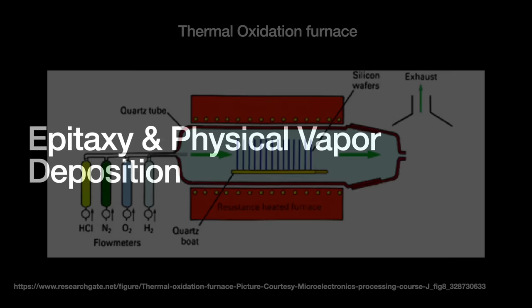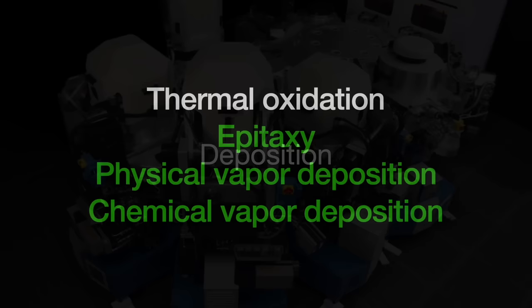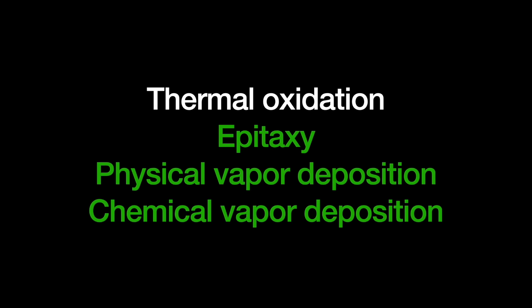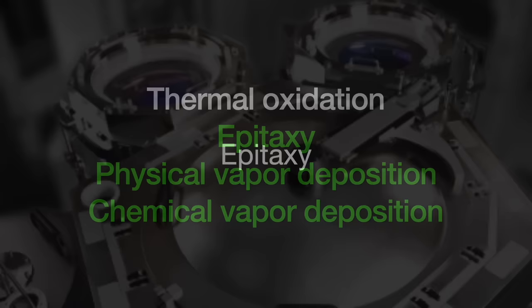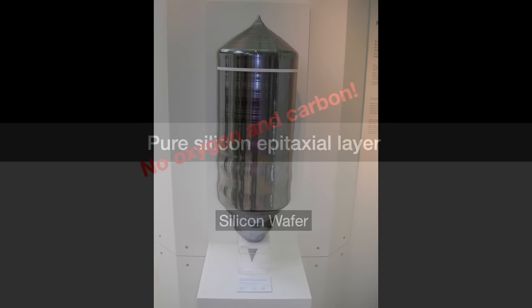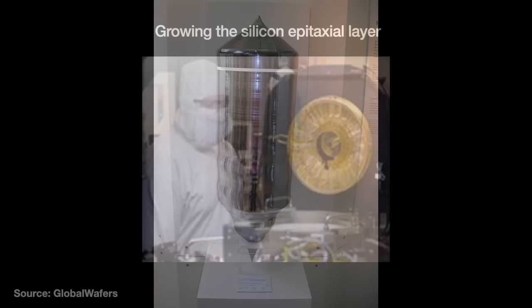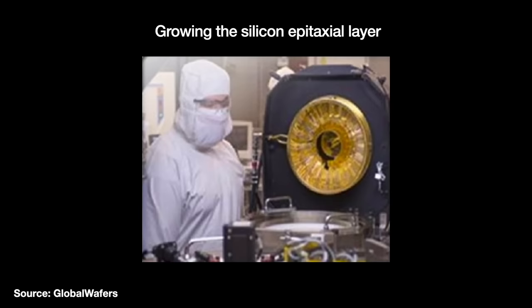Other than silicon dioxide, everything else above the surface of the wafer is deposited rather than grown — ergo the phrase deposition. Because each of these thin films has its own specific requirements for deposition, this industry is very diverse. The three major deposition markets are epitaxy, physical vapor deposition, and chemical vapor deposition. The first is epitaxy. The primary use case is for laying down an epitaxial layer of silicon on top of the silicon wafer. This epitaxial layer is generally free of oxygen and carbon — despite all we do to purify silicon wafers, the Czochralski method still leaves behind oxygen and carbon impurities from the graphite liners and quartz crucible, which impede performance. The epitaxial layer is usually applied by a wafer manufacturer like Global Wafers, but sometimes the IC manufacturer does it too.